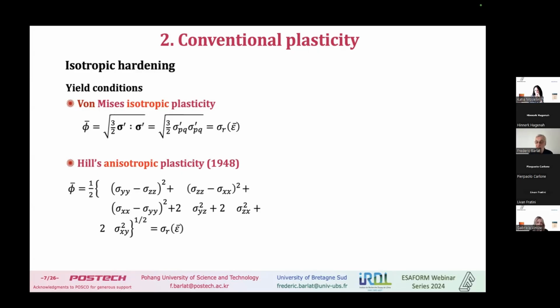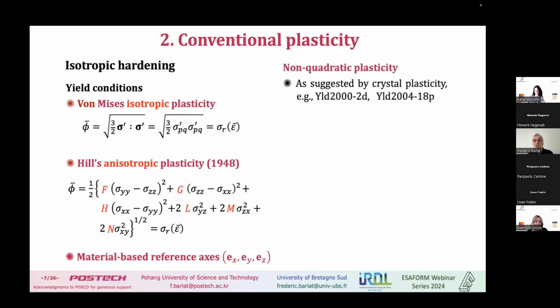And in case of Hill 1948, which is very well known, it's a modification of von Mises with the coefficient I shown here in red on my presentation. The difference with von Mises, beside those coefficients, is that we need a material-based reference axis. Okay, we cannot take any reference base vector, any set of base vector as we would do with von Mises, but we need a reference frame attached to the material, like rolling and transverse direction and normal direction in sheet.